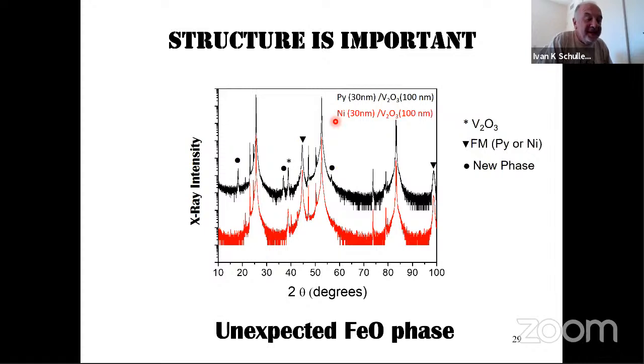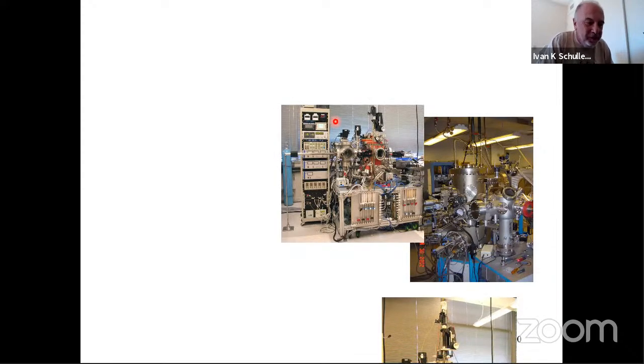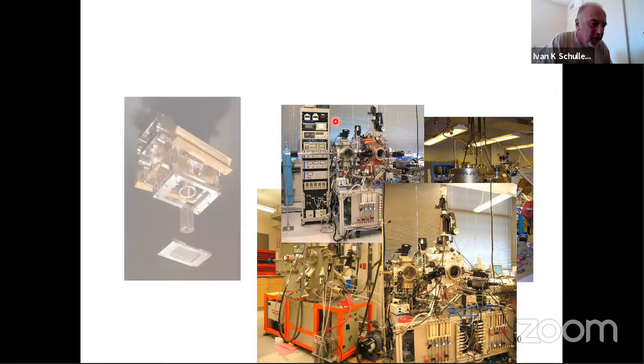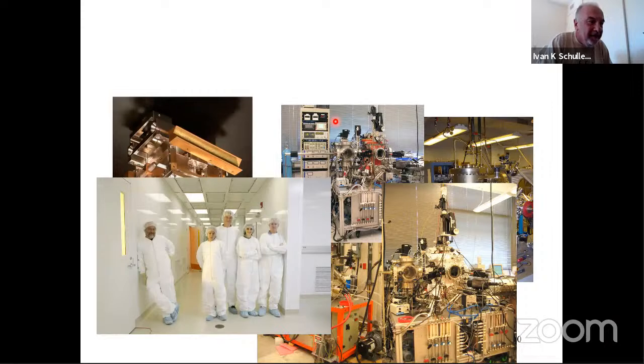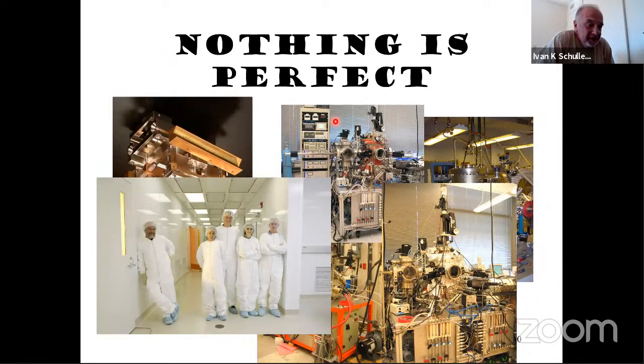The reason that this is a red herring is because at that interface, because of growth reasons, there is a formation of an iron oxide interface, which is totally unexpected. So the layers don't look like you think they look like. And all this is due to the formation of this red herring, this iron oxide phase, which is actually completely uninteresting. So you have to be very careful of that. And it is not that I don't have expensive equipment in my lab. I have every expensive equipment you possibly can imagine. I do have it in my lab, but nothing is perfect. Every time I grow something, there is all.